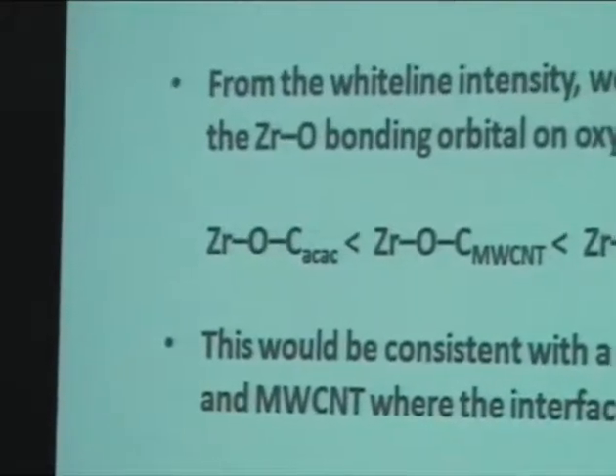Similar arguments will apply for the other X-ray absorption, but I won't do them in such detail as I do here. So the argument goes that the intensity of that white line is determined by the density of empty states at the Fermi level. If you have more empty states, you get higher intensity, as you do with the precursor, the acetylacetonate. If you get a lower intensity, that means that there's more electron density and fewer holes near the Fermi level.